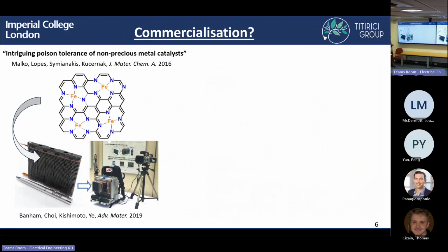And so, considering commercialization, one of the other benefits of these precious metal-free catalysts compared to platinum is they have this poison tolerance. This has been introduced before by Anthony Kucernak, where they found that these types of catalysts are less prone to poisoning from contaminants in, say, your feed compared to platinum. There are specific examples already employed where, if you have a very poor quality air in the case of a fire and you want a backup power supply, it would be more beneficial to use these non-precious metal catalysts. And that's actually being used in a case in Japan.